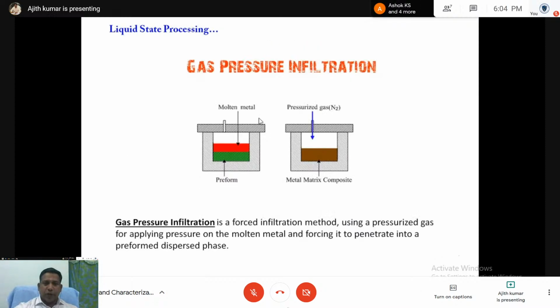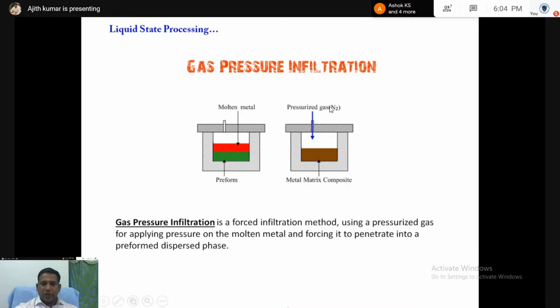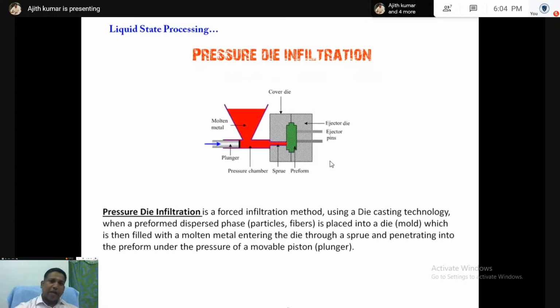This is called squeeze infiltration. Again, one is gas pressure infiltration. Instead of a press, we use gas. This uses high pressure gas, high pressure nitrogen gas, or the gas will vary with respect to the metal. If you give the pressurized gas to the container, due to that pressure, the molten metal will infiltrate into the preform, then we will get the composite. Another one is pressure die infiltration. If you want a component like small gears or small parts, we fix a cavity. In the cavity, we fix the ceramic preform. In that preform, using the plunger, the molten metal will fill into the preform, then we will get the composite material.